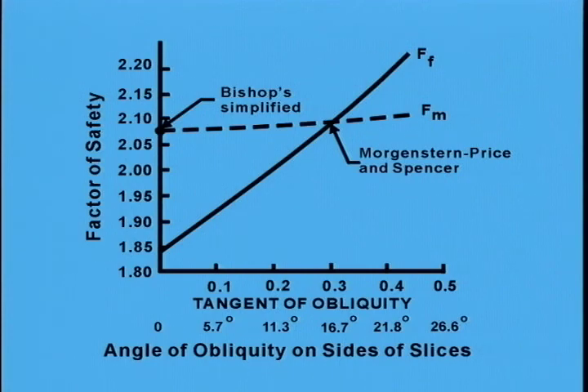The method, however, only applies to circular failure surfaces, while the other two methods can be used for failure surfaces of irregular shape. In the Morgenstern, Price, and Spencer methods, if a composite failure surface is used, a circle may be used to approximate the surface, and the center of this circle used for the point about which moments are summed. This completes my discussion of how I think stability analyses for the rapid drawdown case and the other rapid loading cases should be carried out.